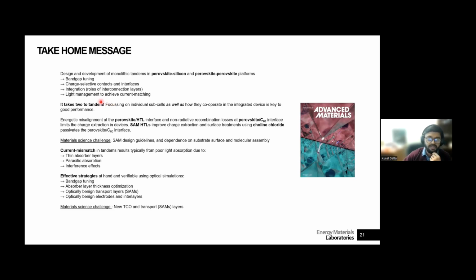And to do that, we looked at how to tune the band gap, which is quite straightforward. How to do charge selective contacts and interfaces, so self-assembled monolayers, interfacial passivation. In the integration end, we looked at the role of this interconnection layer, so the nickel oxide in the case of the perovskite-silicon tandem, and the tin oxide in the case of the perovskite-perovskite tandem. And then finally, light management to achieve current matching between the two cells, which is almost critical at this point to get a high efficiency device.